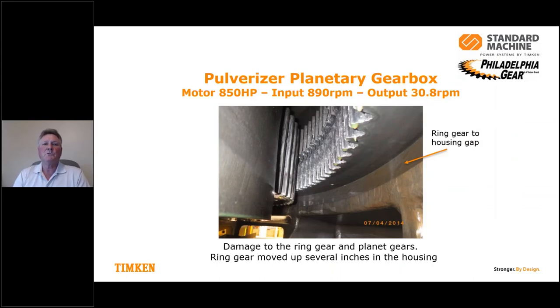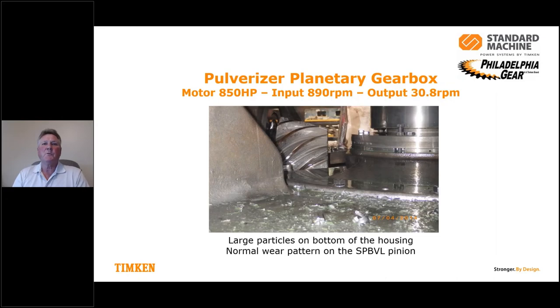In the second motion, which is the planetary section, this is where most of the damage occurred. The first thing we noticed was that the ring gear, which has an interference fit into the housing, had moved. There was a large gap from where it was originally positioned to where it was when we opened the gearbox to do our inspection. And that's an indicator there's some sort of forces going on in that gearbox that move that ring gear. So we continue to look. Down on the bottom of the gearbox where the spiral bevel is, there were a lot of particles, large pieces of gearing laying down in the housing, which we expected with that kind of damage. But interestingly enough, the spiral bevel gear was still in very good condition.